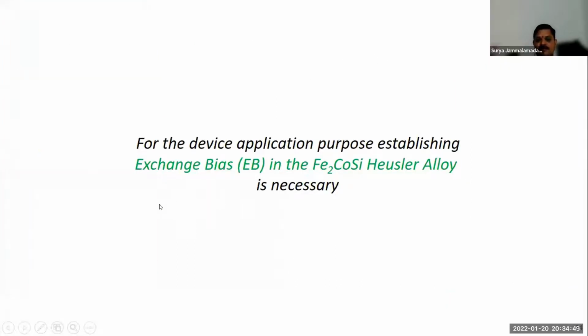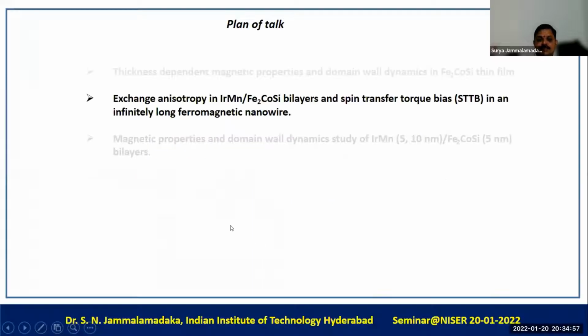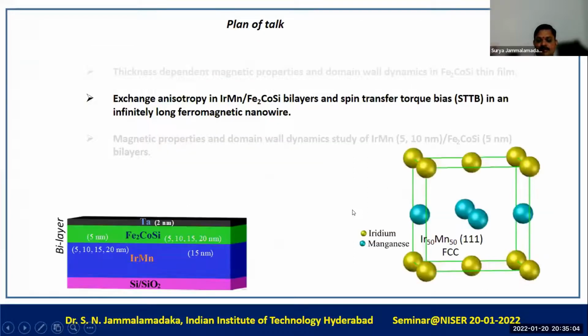So now the question is, for device applications, it is very important to establish the exchange bias. For that reason, we tried to deposit the Fe2CoSi film on top of the iridium manganese antiferromagnetic material. On top of Fe2CoSi, we deposited tantalum. The thickness of the tantalum is 2 nanometers, which acts as a capping layer. Essentially, we wanted to establish an exchange bias phenomenon in this system, iridium manganese and Fe2CoSi. The structure of the iridium manganese is depicted over here. It actually attains a face-centered cubic structure.